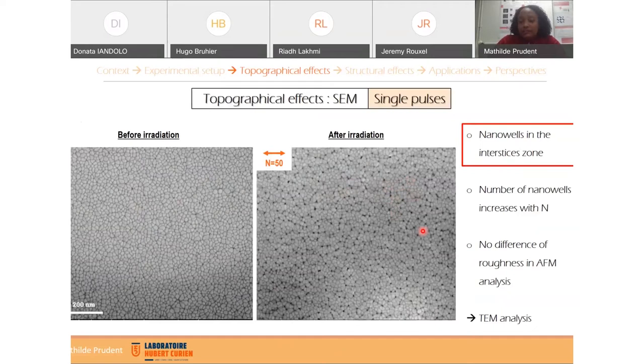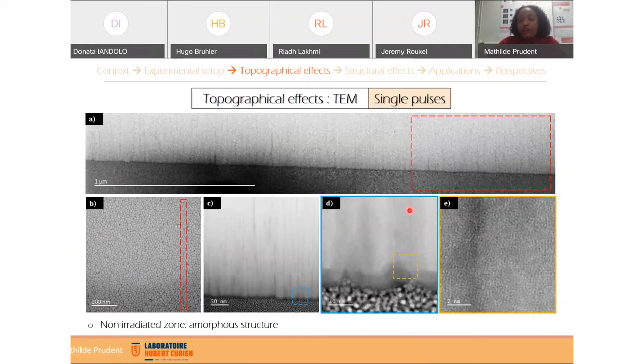So here you can see the results of the TEM analysis for a non-irradiated zone. For this analysis, we just extracted here some FIB lamella, and we realized the TEM analysis on this FIB lamella. You can see here that we have a very low roughness, in accordance with the AFM analysis. And we can see two shades of color. So one color in the surface of the sample and another color in the subsurface of the sample. Also, this analysis shows us that we have an amorphous zone in all of the FIB lamella.